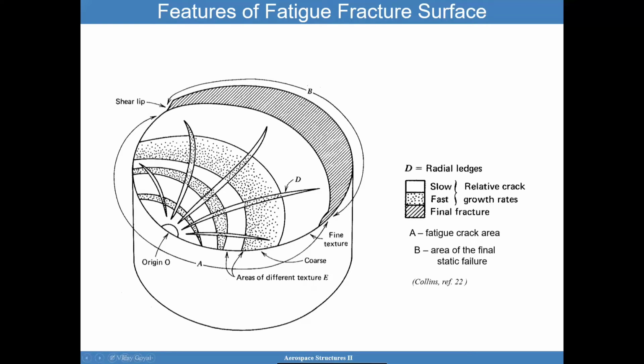So region A, which is right here, all in white, we're going to call the fatigue crack growth area. Over here, the shaded area is a final static failure, or the ductile failure, or the brittle failure that occurred suddenly. And I want to point out a few things. In these regions where it's not shaded, the crack tends to be slow. And then you're going to have regions where the crack growth tends to be faster. That's what causes these beach marks in the first place.